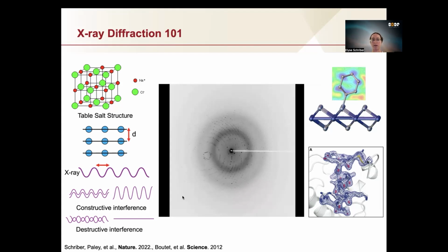These reflections are essentially a fingerprint of that atom's position in the lattice, and they change and move as different lattices become in the Bragg condition, and this is all a result of this constructive and destructive interference process. This GIF here shows how X-ray diffraction works. We start to see that different spots show up at different intervals, and this is a result of the crystal being rotated through the lattice.